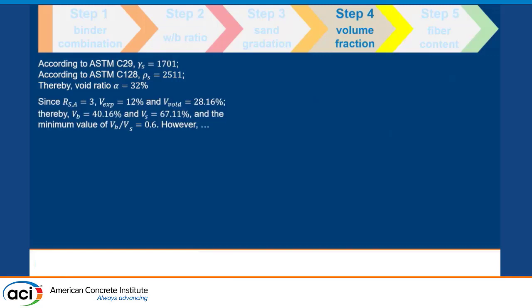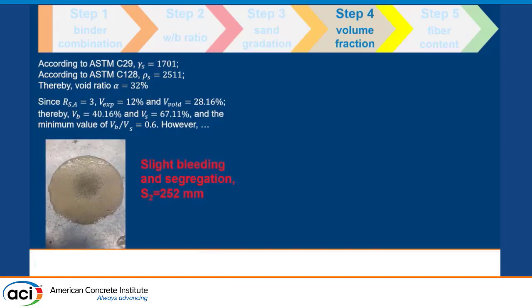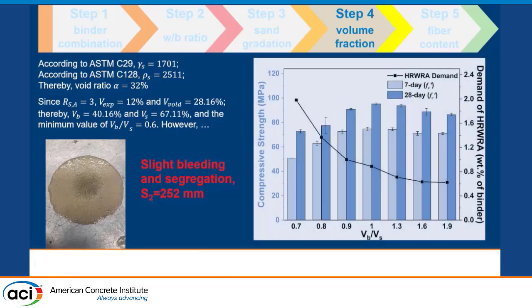After doing the ASTM C29 and C128 tests, we can obtain the bulk density and density of the blended sand so that the void ratio can be determined. Then we obtain the minimum value for the V_B over V_S ratio of 0.6. However, if we directly employ such a minimum value, the mixture will show some slight bleeding when we try to achieve the flow diameter of 280, and the best we can do is only 252. So we started from 0.7 of the ratio of V_B over V_S up to 1.9, and the optimum ratio of V_B over V_S is determined to be 1 according to the compressive strength and demand for high range water reducer in the mixture.